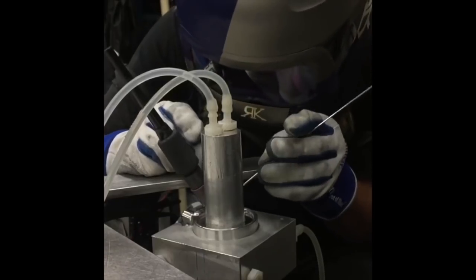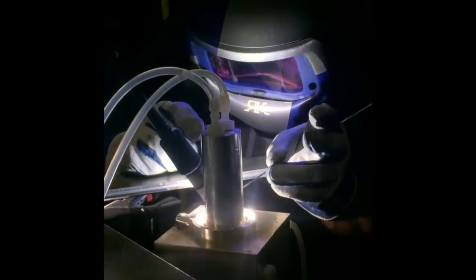In one of the fab shops I worked in, they did quite a bit of galvanized pipe, and even though the coating was removed before welding, there'd always be a little bit left over. That cover pass, on the toes of the weld, would bring it out.